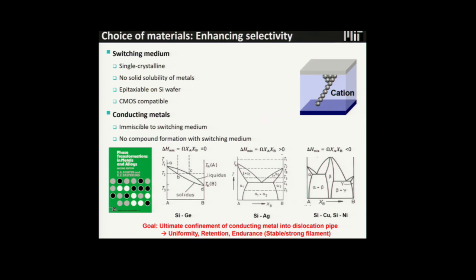So very important requirements: there shouldn't be any solid solubility of metals into the switching medium. Also, it has to be epitaxial on a silicon wafer to be compatible with the current CMOS process. The easy answer is cheap silicon wafer. Now, how can you make a dislocation in silicon? You just grow silicon germanium on silicon, then there is a lattice mismatch between silicon germanium and silicon, so you can easily make a threading dislocation by changing the lattice mismatch. So we picked silicon germanium as a switching medium.